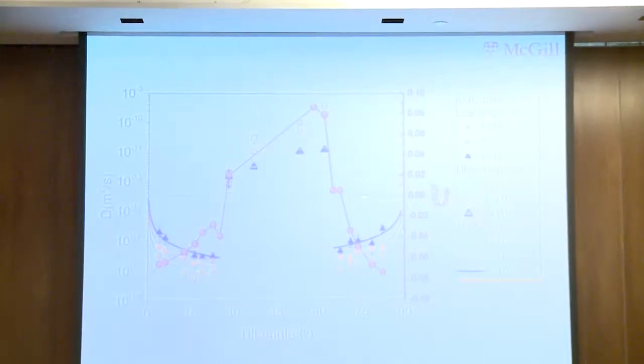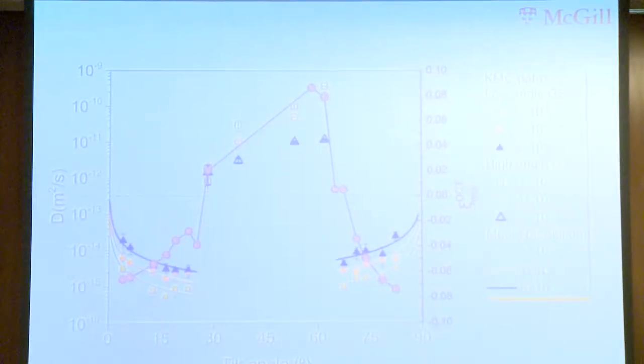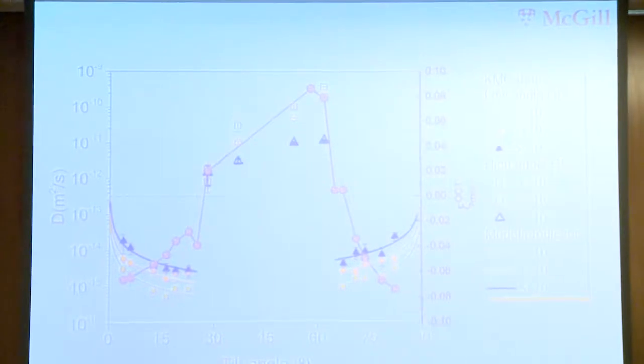If you look at the volume distortion, of course this line is not supposed to be this. I don't know whether I have time to describe it, but if you look at the constituting polyhedron volume, then in this region the distortion is much more significant. So there's more facilitation of hydrogen diffusion. Distortion is larger? Yes, it's larger. But this is a very localized distortion of the single polyhedron. So this is just one possible reason for the difference. Okay, we can discuss further.